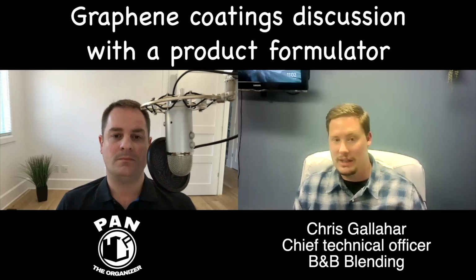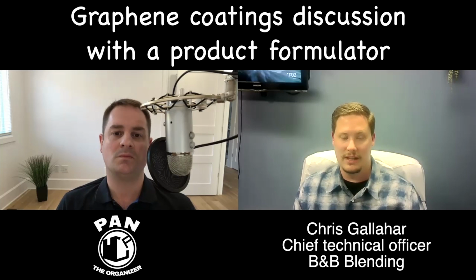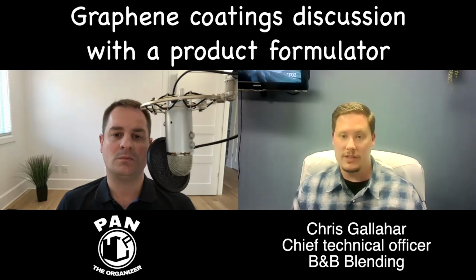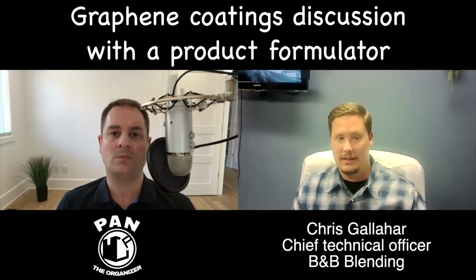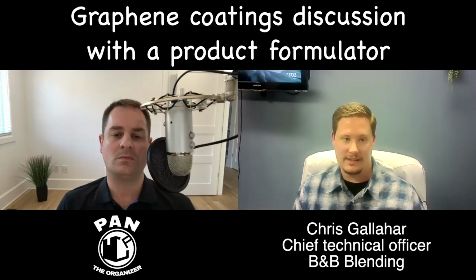And then we're throwing it in the instrument to see if it yellows, cracks, peels, if it delaminates, if it keeps the surface more colorful and stable behind it. We're using all those instruments to then inform us, is this actually an improved resin or not? Things like the pencil hardness, as well as measuring coating film thickness, or even things as rudimentary as dripping the resins natively onto glass substrates and watching how long they take to cure and how clear they are, how smooth they are, how fast it happens.